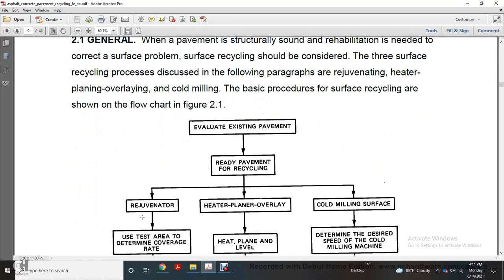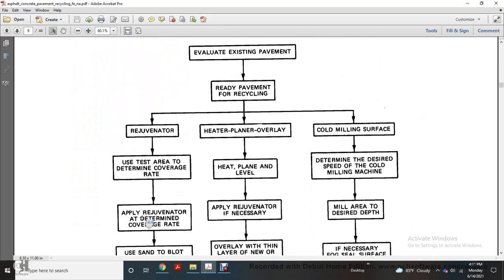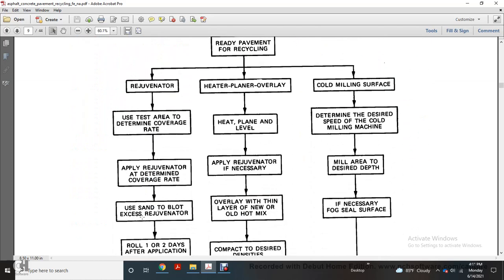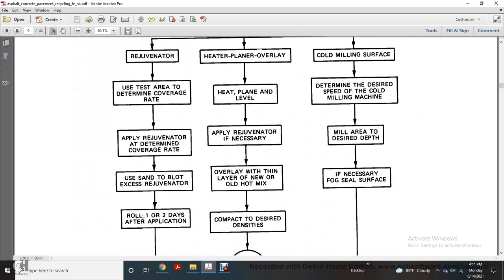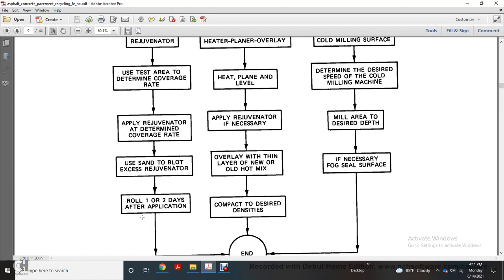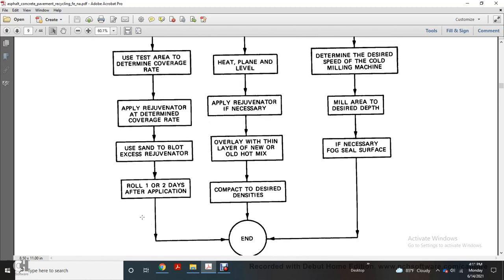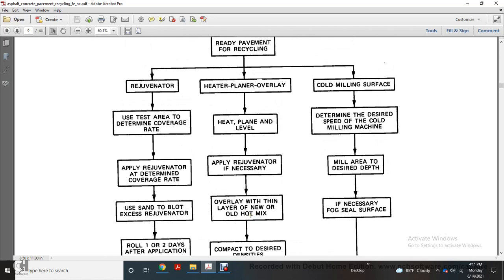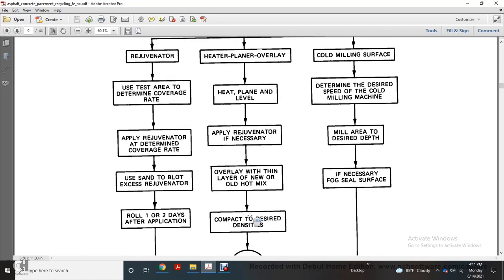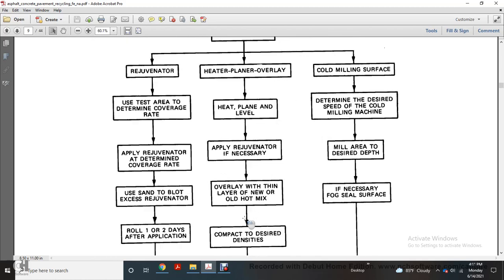Evaluate the existing pavement to see if it is ready for recycling. For the rejuvenator, use a test area to determine the application rate. Apply the rejuvenator at the determined coverage rate. Use sand to blot the excess rejuvenator and roll one to two days after application. Then, for heater plane overlay, heater plane and level apply rejuvenator if necessary. Overlay with a new layer of hot mix and compact to the desired density.